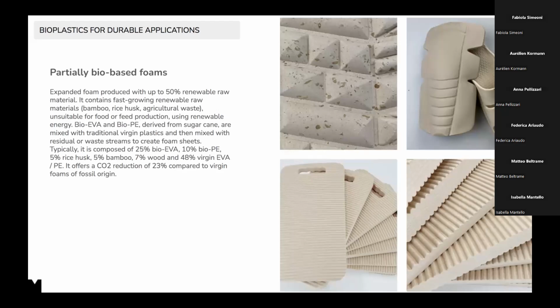This is an EVA that would use instead micronized fibers, a part of bio-based polymers and a part of micronized straw as a filler. This is not used for cushioning applications, but mostly for semi-stiff applications like slippers or other types of object like boards, like these in the pictures. In this case, again, the company has measured the CO2 reduction by using this quota of bio-based materials, which is 23% compared with the virgin foams of fossil origin. They produce both, so they have made an easy comparison between the two materials.